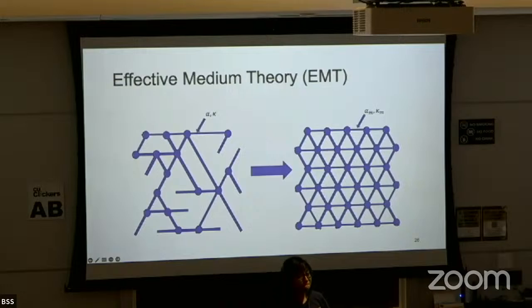Isotropic, but even if these have the same shear modulus, presumably the network on the right would fracture at a much lower strain, since it is more densely cross-linked, or is that not the right way to think? Yeah, so fracture is a very different thing, and there, of course, the actual configuration matters. So you are absolutely right. Here, in the mean field sense, we are only thinking about the effective shear modulus. And when I wrote down the energy, remember, I wrote down everything in the small deformation limit. I'm only focusing on the linear response regime, at least for this part. When you have nonlinearities, and fracture is a very nonlinear phenomenon, things will change. I am hoping to talk about fracture on Friday, the last day.